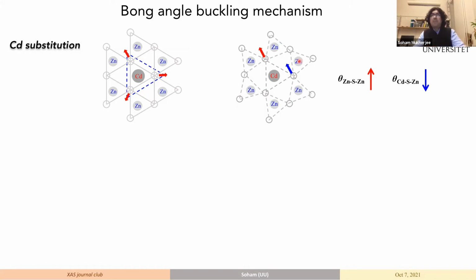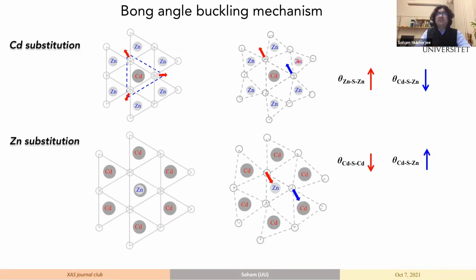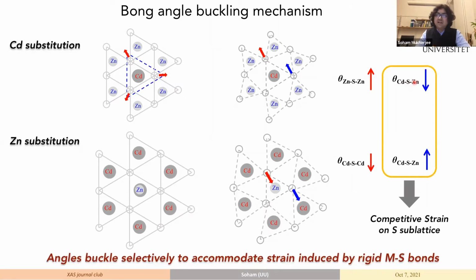When you do the reverse, you see that exactly the opposite thing happens. There is a local shrinking of the tetrahedra, and then this sulfur is now being pulled towards the zinc. This will reduce the cadmium-sulfur-cadmium angle, which is exactly what you see in the experiment. But now this zinc-sulfur-cadmium angle will try to increase. So there would be a competitive strain on the cadmium-sulfur-zinc angle, which explains why this particular angle lies in between zinc-sulfur-zinc and cadmium-sulfur-cadmium. So what we see is that the angles buckle very selectively to accommodate the strain that you have put in the system by doping at one particular site.